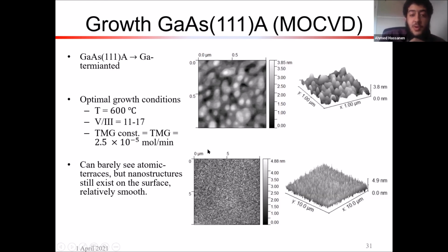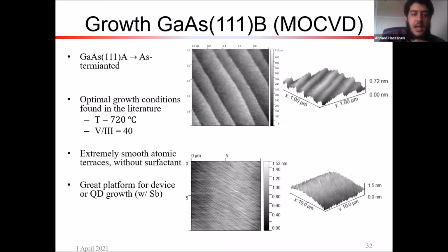But the interesting thing was when I tried growing on 111B, and again, this is without surfactants, just normal growth. I used a temperature of around 720 Celsius and a V/III ratio of 40, and you can see you get very, very smooth atomic steps. So this is sub-nanometer roughness. This is very smooth.